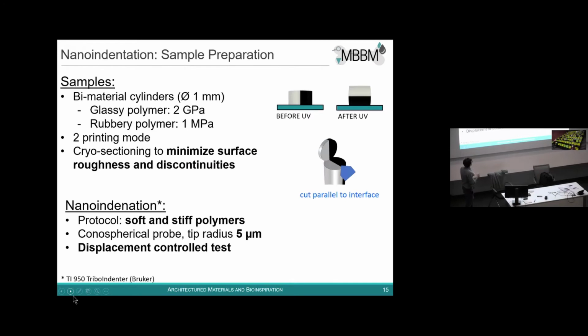So I think here I can go a little bit quicker. We first prepared the samples for nano-indentation. We printed small samples where the interface was formed before UV curing. And by changing the orientation of the samples, we obtained samples with the interface formed after UV curing. Then for nano-indentation, we need a very smooth surface, which is a little bit tricky when you have polymers with such big differences in mechanical behavior, because you cannot do standard polishing from metallurgy. So what we did here was cryomicrotome cutting. And so we had a very smooth surface, with nanometer scale roughness, and then we could nano-indent.